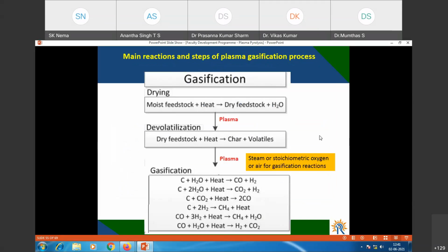And you can see again the plasma gasification. From the feedstock, initially you are removing moisture, and afterwards this waste is broken into char and volatiles, and then in the presence of plasma, if you are adding controlled oxygen, the equivalence ratio varying from 0.25 to about 0.5, this oxygen you are adding in substoichiometric ratio, then you are able to generate these different molecules, useful gases in the plasma gasification.